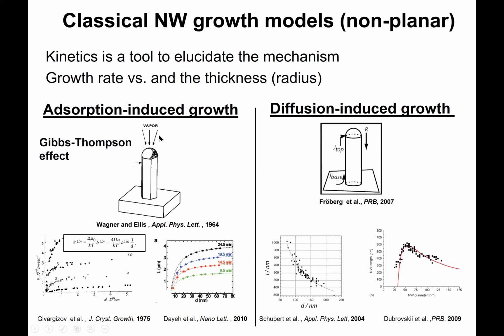...the material is coming from the vapor phase directly to the catalyst, and then the solubility of the material in the catalyst nanoparticle depended very strongly on the size because of the Gibbs-Thomson effect, which relates the chemical potential to the curvature. This is the reason why smaller particles have a lower melting point.